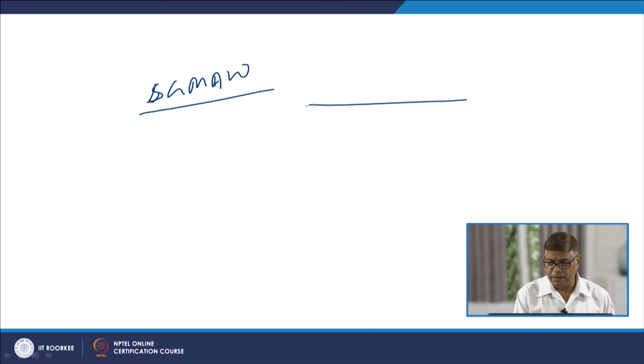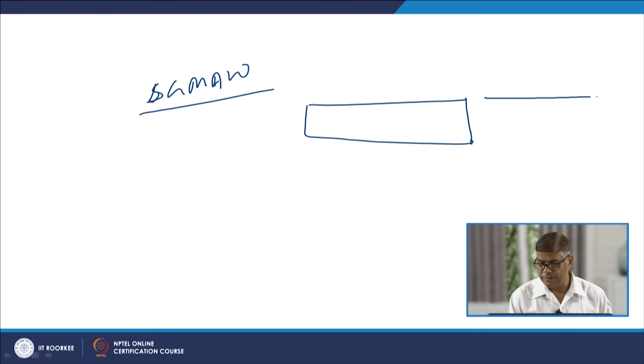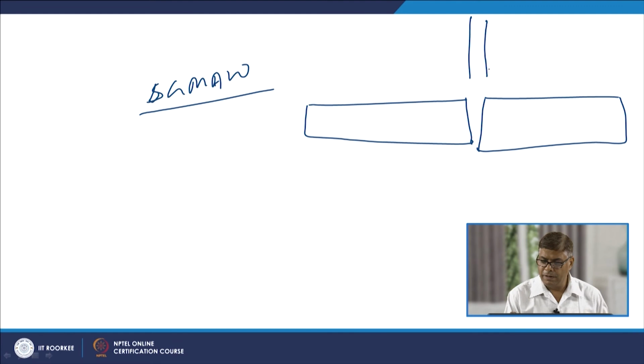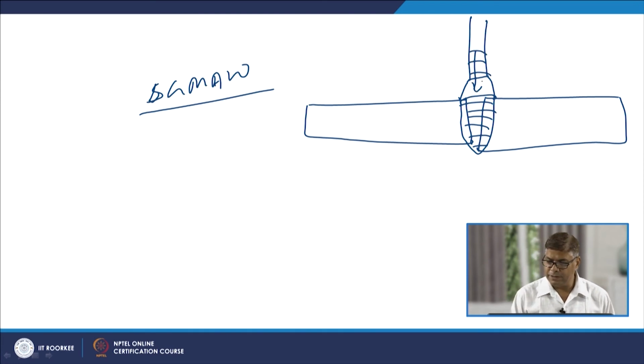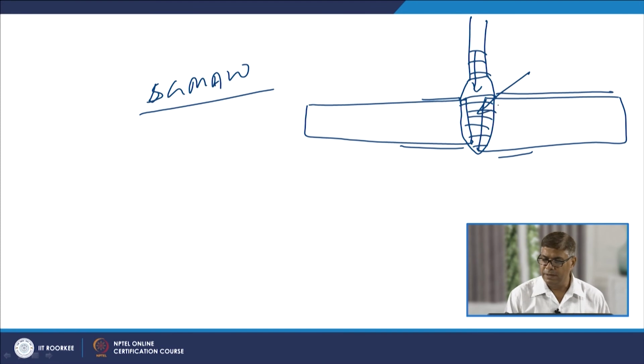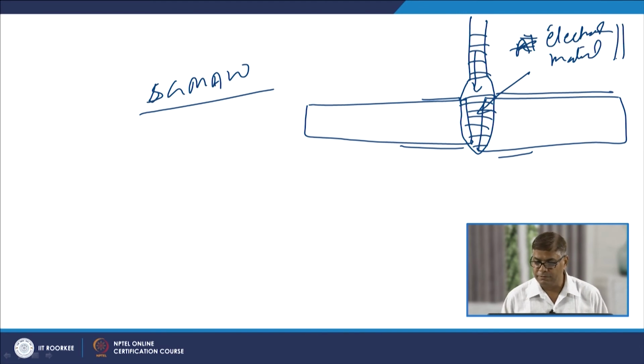On the other hand, when we talk of the GMAW process, it is a very different process as compared to the GTAW process, where the filler in form of electrode will be developing the arc and generating the heat. At the same time the electrode will also be melting and getting transferred into the weld metal. The advantage of this is that whatever aluminum is coming from the base metal due to the fusion will be diluted by the electrode material coming due to the consumption of the electrode during the welding process.